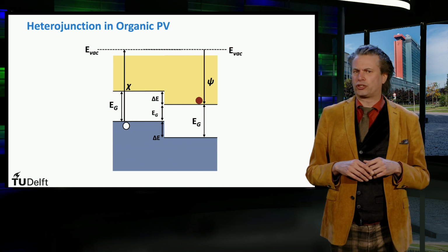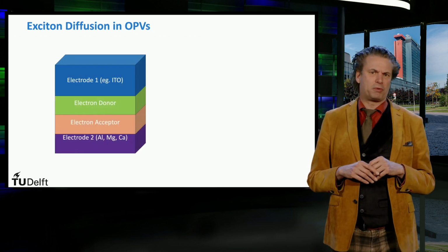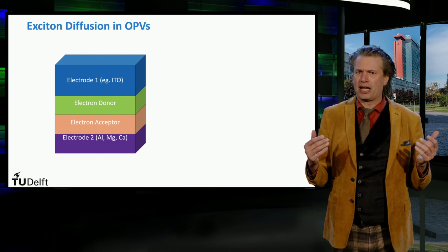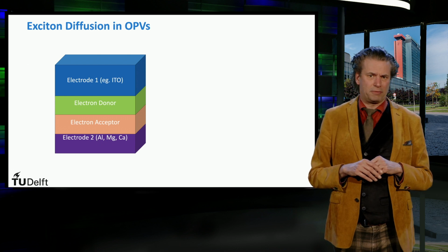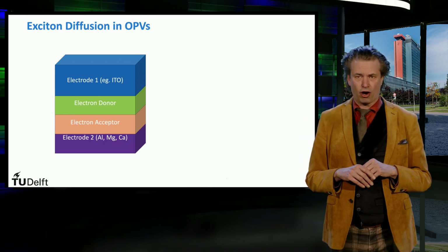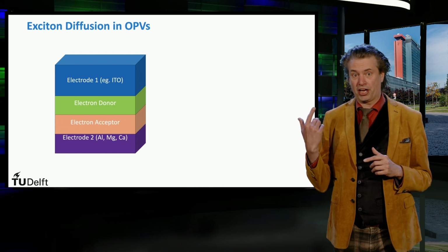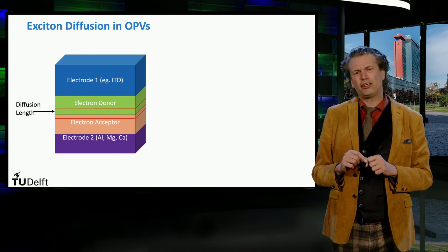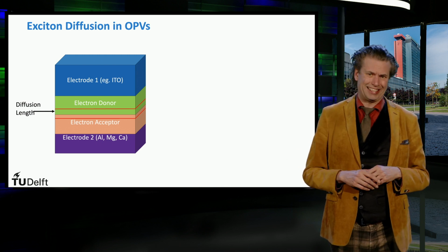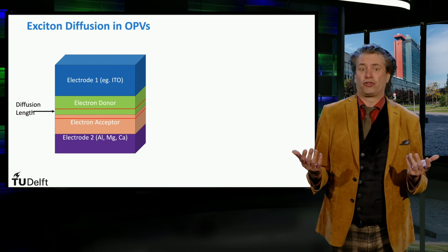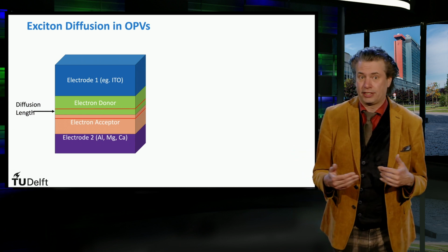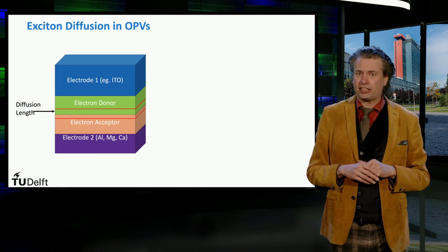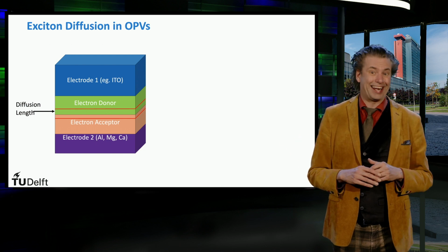In a normal heterojunction organic solar cell, the organic absorber material exhibits a high absorption coefficient and hence requires an absorber layer with a thickness of anything more than just 100 nanometers to maximize the utilization of the solar spectrum. On the other hand, the inherent nature of the excitons to recombine easily gives a diffusion length of around 20 nanometers. The total thickness of the solar cell must however be limited by its diffusion length, which in this case is much shorter than what is required for a satisfactory absorption of the incident light.